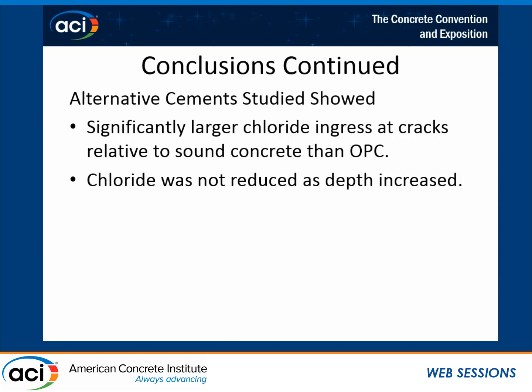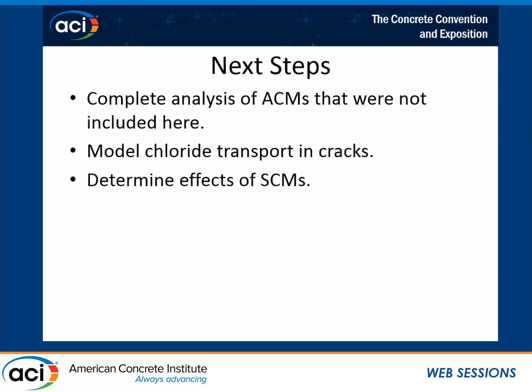And that's for those of you who just look at macrocell, you've got to look at the sample later on and actually look at your bars, because that tells you an awful lot, especially when you see your macrocell current dropping after it was high for a long period of time. That's almost a dead giveaway, because the 2 bars on the bottom in this particular test are corroding. Next steps: complete the analysis of the ACMs that were not included here.